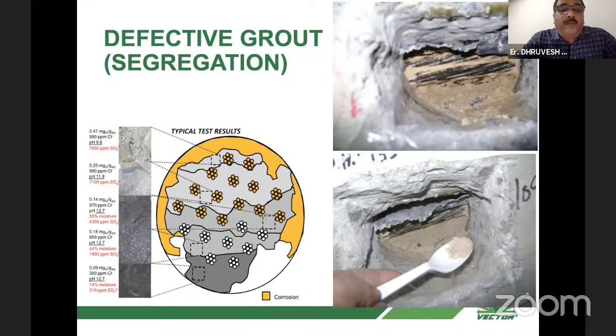Second, apart from the void, this is the picture which is showing segregation, like defective grout. If the grout has more chlorides or sulfates, you can see the lower end is very dense, and the upper end has voids, or maybe it is fully grouted, but the grout quality is such that segregation has happened, and the top portion of the grout is not able to protect the upper strands or upper surface of the rebar, or maybe the underneath of the sheath, from corrosion.